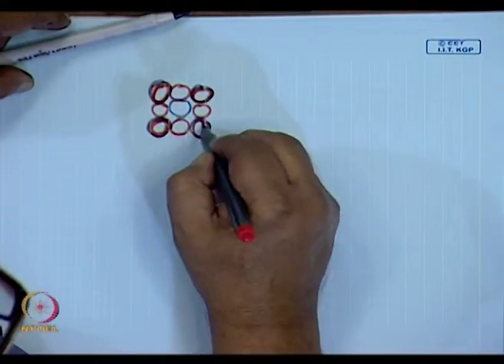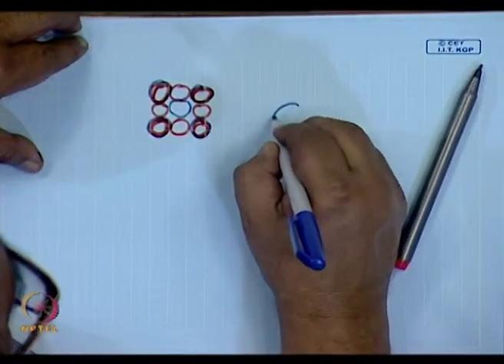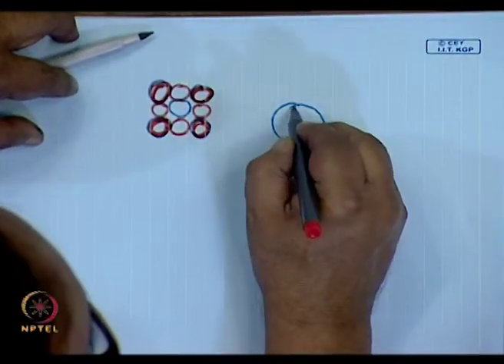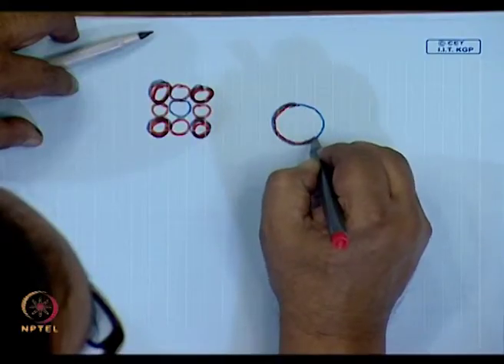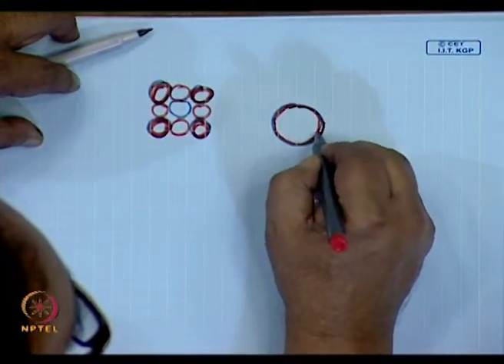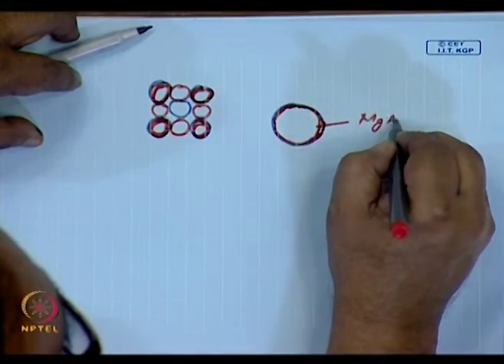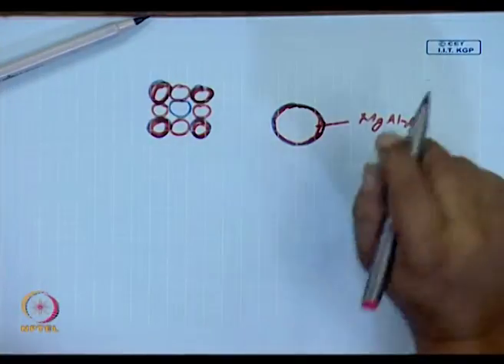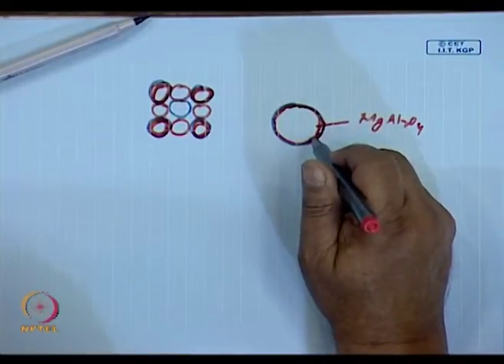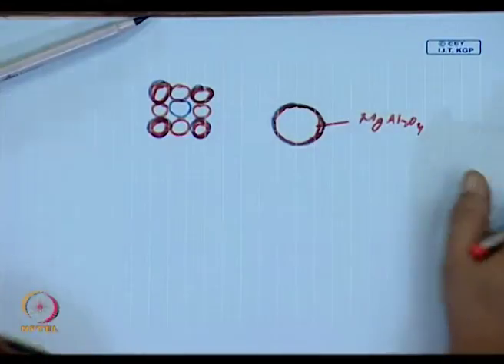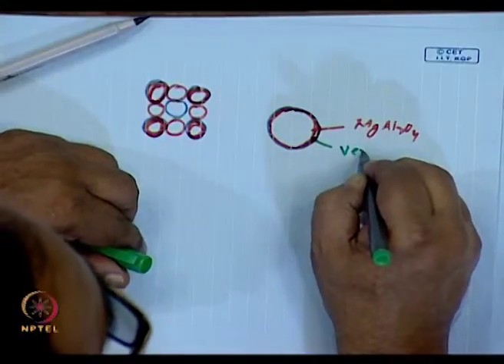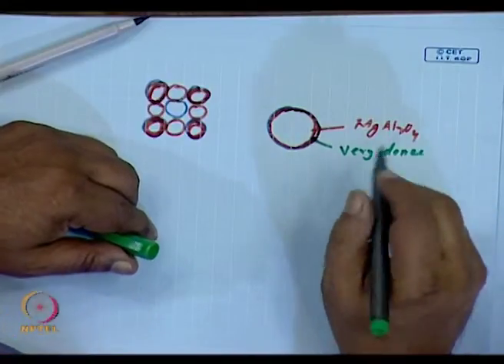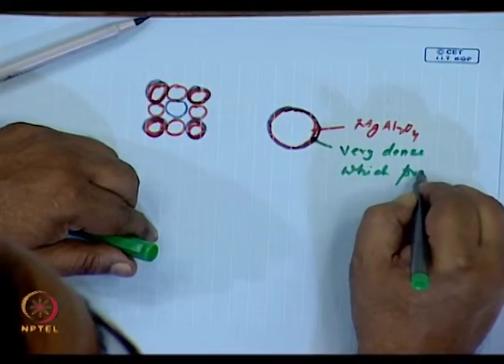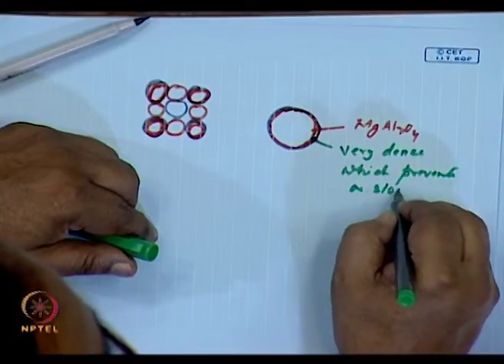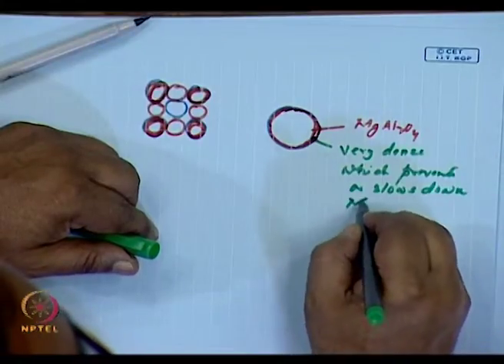So, what we have now is the Al2O3 grain whose first few molecular layers have been converted to MgAl2O4. Now, this poses two problems. One, this MgAl2O4 has been formed due to a molecular reaction. Hence, this layer is very dense, which prevents or slows down MgO diffusion.